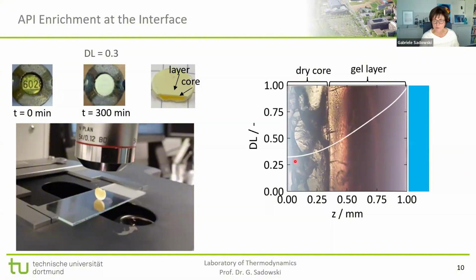So what Dominic Bormann did is he calculated the concentration profile. So this is drug load as a function of the point where we are. So this is the inner of the tablet where we have the desired drug load that we had in the tablet at the start of the experiment. So this is still 0.3. Whereas the drug load is increasing, and that means directly at the gel layer, we have a drug load of almost 100%, which means